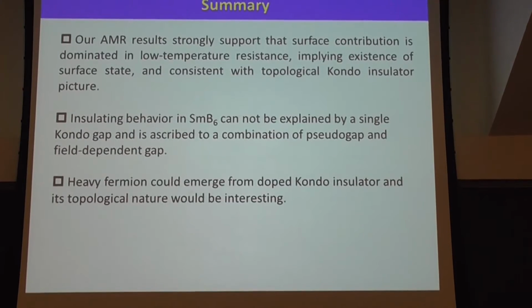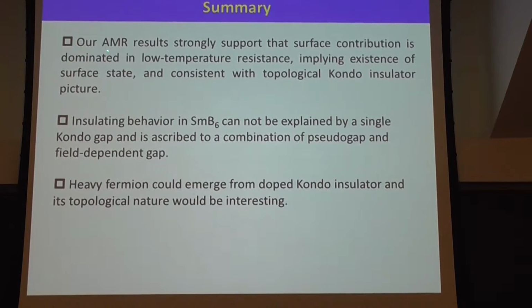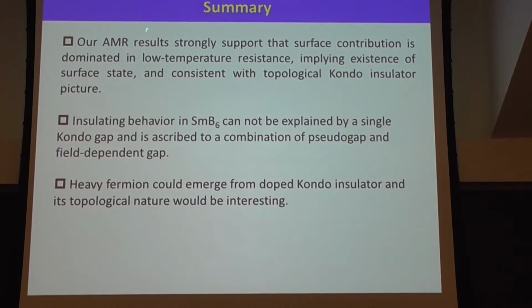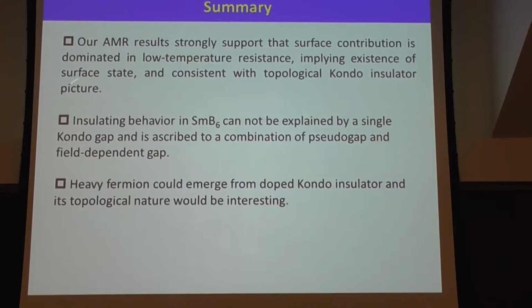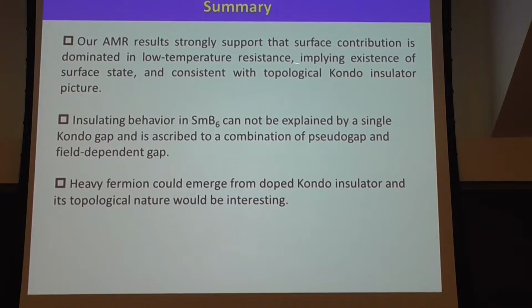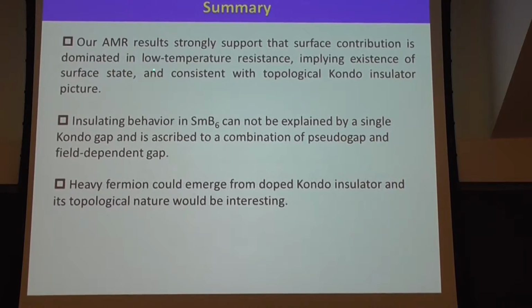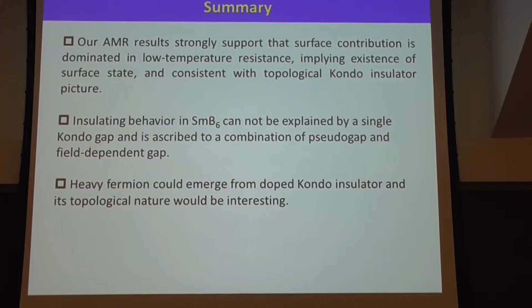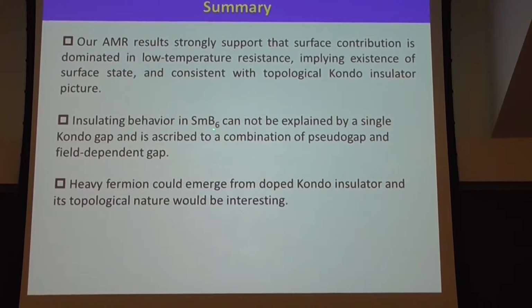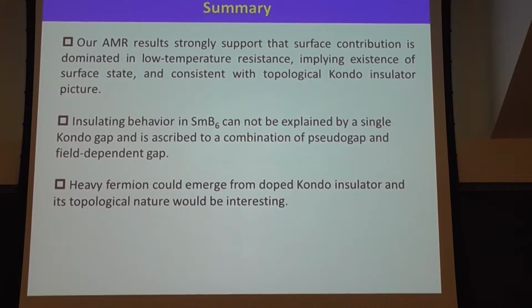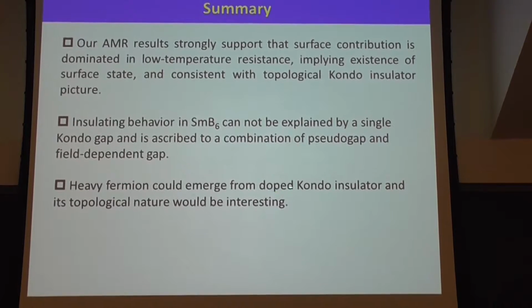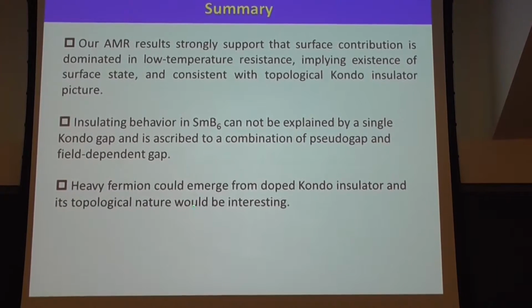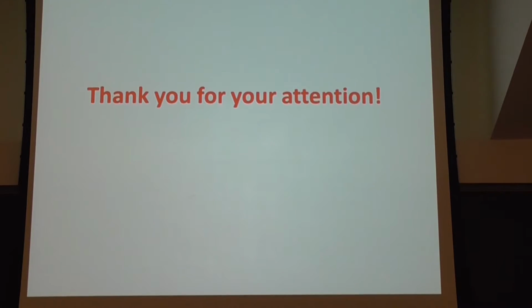Okay, let me give a summary. Overall, the AMR results strongly support that the surface contribution dominates the low temperature resistance, implying the existing surface state. This is consistent with the topological insulator picture. Also, the insulating behavior in this hexaboride cannot be explained by a single Kondo gap. It is ascribed to a combination of a pseudogap and a field dependent gap. Also, heavy fermion could emerge from doped Kondo insulator, and its topological nature would be interesting. Okay, thank you for your attention.